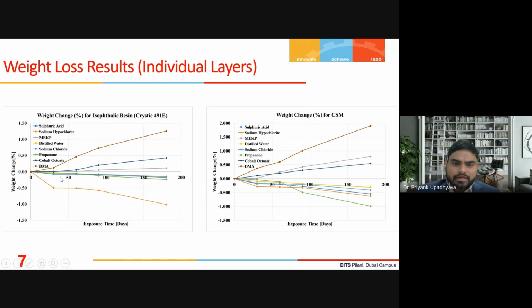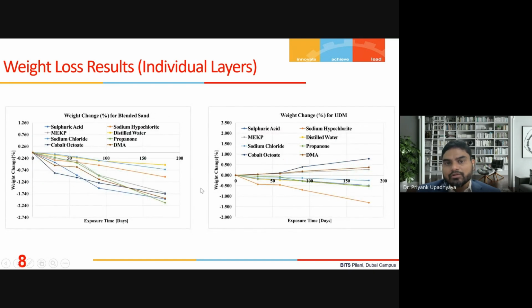The percent reduction is very small, about 1% after completion of 180 days. Now the next two layers are blended sand. This is a porous layer because we are mixing sand with resin, so there is a lot of void content there. What we notice during the experiment is that some sand particles start chipping away from the samples. That's why you can see a consistent reduction in all the samples here.